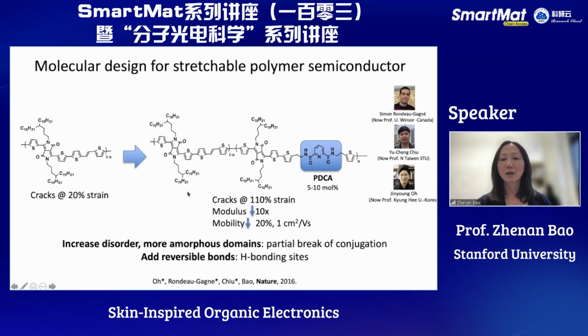And this can increase the crack onset strain from 20% to 110%, and the modulus decreased by 10 times. And that, we found, is still not sufficient, because if we use a simple linear chain, the crack onset strain is still only around 50%. So to further improve that, we added hydrogen bonding sites to add additional ways to introduce disorder and weak non-covalent bonding. And this resulted in a much more robust film. Even though there's a decrease in the overall mobility, the mobility of this resulting stretchable polymer can maintain the same order of magnitude as amorphous silicon, but with added stretchability.